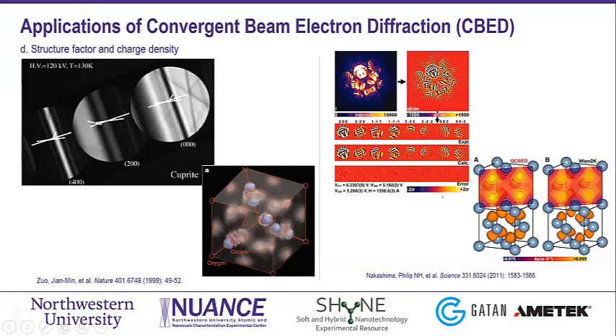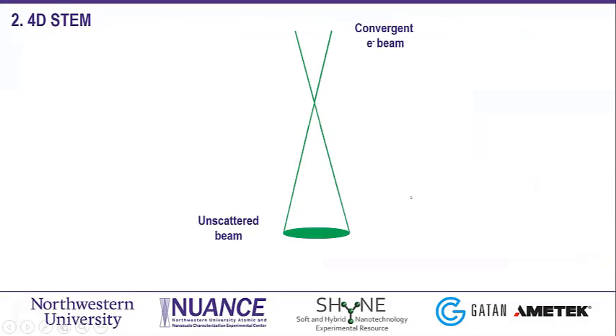A little bit more recent example here, folks from Monash in Australia used a condition that is closer to the zone axis to similarly determine the charge density distribution in an aluminum sample here. So as you can see, there is a lot of information that you can extract from CBED, and we just scratched the surface there.